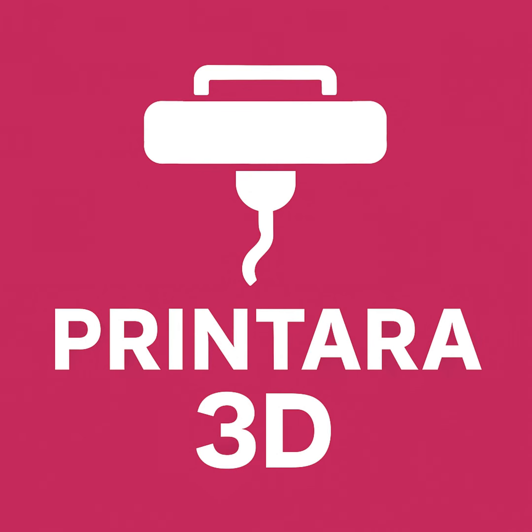And speed. How fast can you realistically print PLA? PLA is pretty forgiving, speed-wise. You can get functional parts printed anywhere from, say, 40 millimeters per second up to maybe 100 millimeters on many printers. But if you want the absolute best visual quality, really smooth surfaces, sharp corners, you need to slow it down. Probably keep it in the 40 to 60 millimeters range. Speed is generally the enemy of surface finish quality.